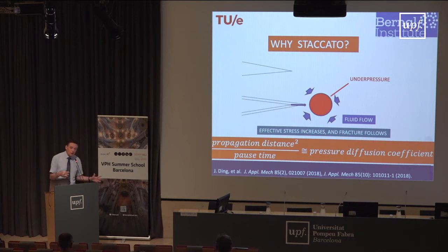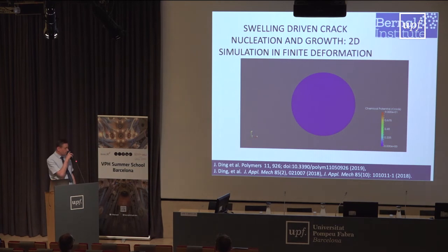It is the hydraulic permeability times the stiffness. And you find, therefore, that you can assume that this stepwise propagation is directly associated with fluid flow inside our gel. Now we can also do simulation of several cracks at the same time in finite deformation, and you see them propagating and going inside, as you would expect it to happen in a gel, but also as you would expect it to happen in an intervertebral disc.